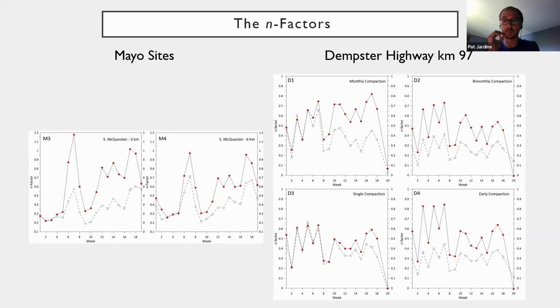And here we have the weekly N factors, which were calculated using air temperatures from Mayo Airport and kilometer 97 of the Dempster Highway during the study period. Typical freezing N factors are between 0.1 and 0.7 in northwestern Canada, and all of the undisturbed plots fell within this range. MU3 and MU4 had an average N factor of 0.39, while MC3 and MC4 had an average N factor of 0.59, for a 0.2 increase. At the Dempster sites, the average N factor at the undisturbed plots was 0.36, and at the compacted plots, it was 0.52, for a 0.16 increase.